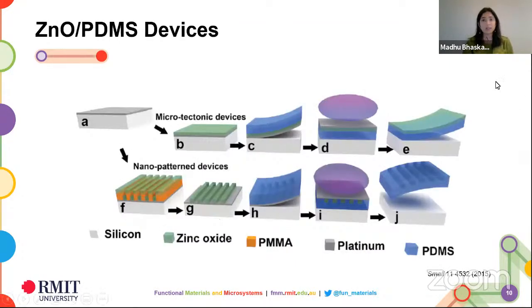We thought, great, we managed to get this working. We managed to take indium tin oxide and make it work on PDMS. What if we try other oxide layers or other oxide devices? So we tried the same process with zinc oxide, and exactly the same process, nothing really changed except for the fact it's now zinc oxide deposited by sputtering. And we realized that you could do the same process again. It still works as a transfer process for zinc oxide on PDMS devices.